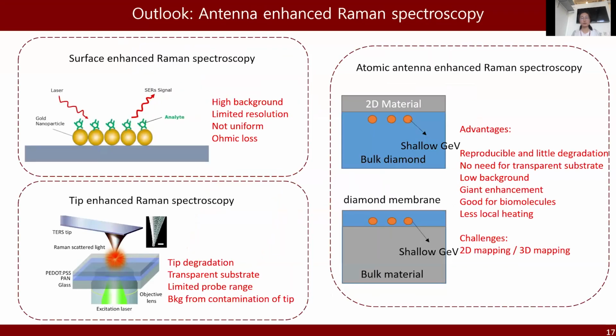So finally, I want to briefly mention one potential application of this atomic antenna, which is called antenna-enhanced Raman spectroscopy. Currently there are two common methods to enhance Raman signal. The first is called surface-enhanced Raman spectroscopy, where people put a lot of gold nanoparticles beneath the material that they're going to measure. Those gold nanoparticles function as optical antennas to enhance the Raman signal.